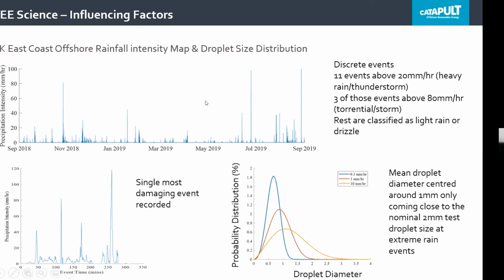The top graph shows the precipitation intensities measured over the period of 1 year. You can see that in this case, there were only 11 events of what we would consider high precipitation intensity. Those 11 could be classified as heavy rain or thunderstorm. That relates to a rainfall intensity of 20 to 25 millimeters per hour, and that 25 millimeters per hour has historically been used in aerospace as the setting for the rain erosion test requirements.